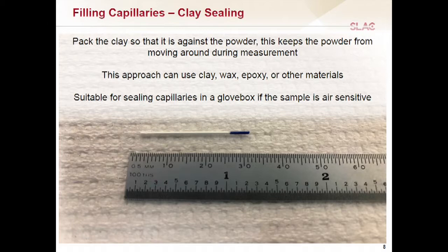If you do this inside of a glove box, make sure that you're not bringing in something that contains a lot of water. But this is a fairly nice approach, and this is much more amenable to doing inside of a glove box for something that's air sensitive, although in the case of clay, I would wonder exactly how well sealed that end is. So probably fine to measure. If I then just let it sit out for a month, I would be a little bit skeptical, but I could easily be wrong on that as well. It may be quite good. If you do something like wax and you melt it, that should be a pretty good seal. Okay, I think that's where I end.